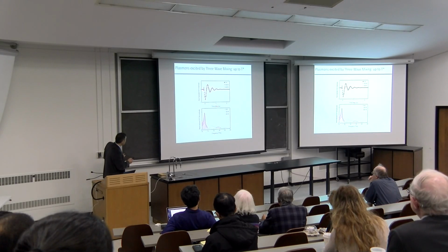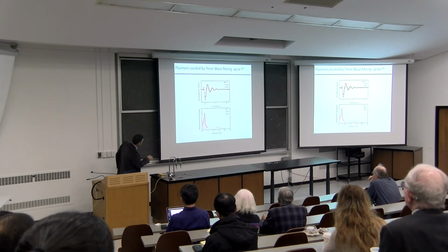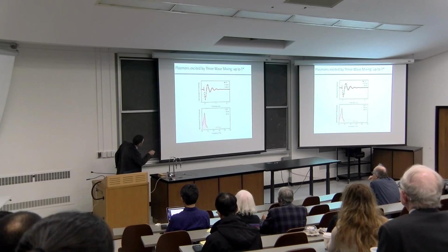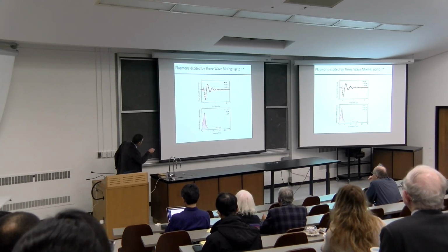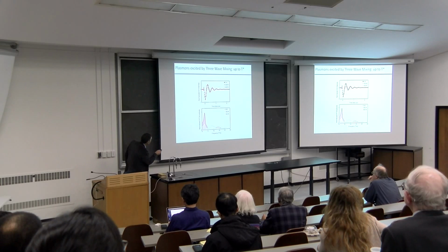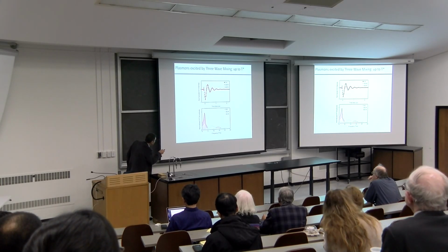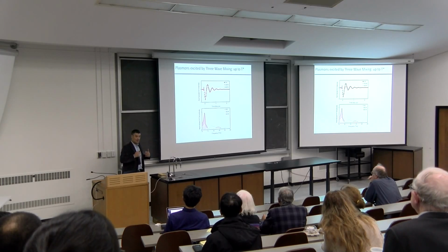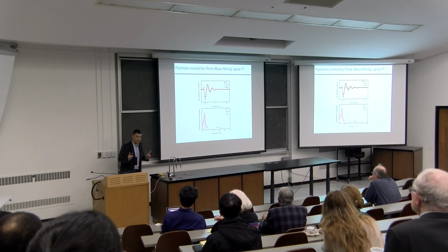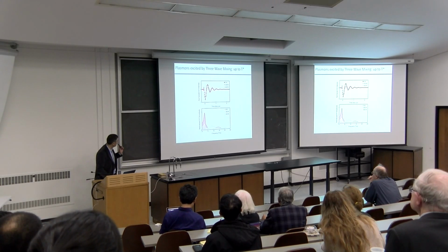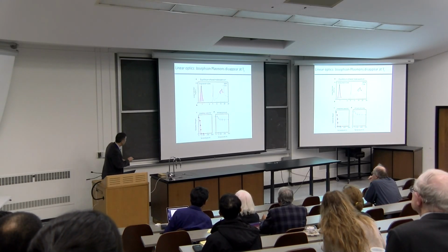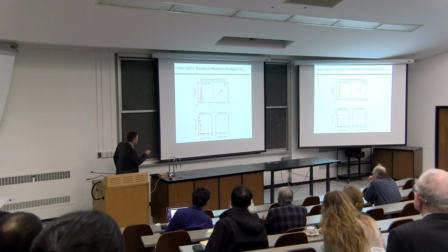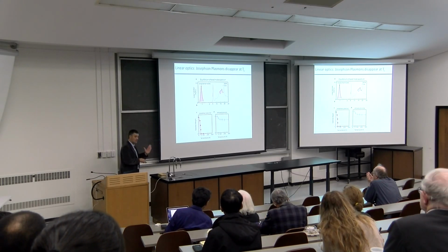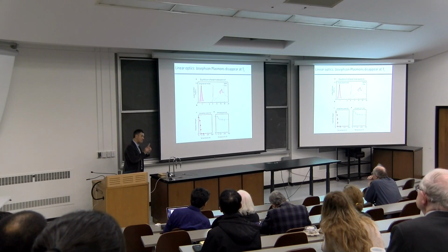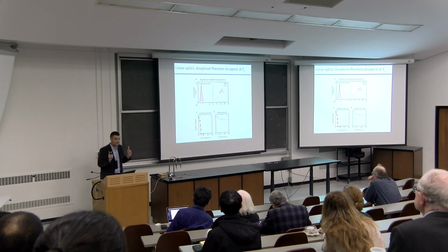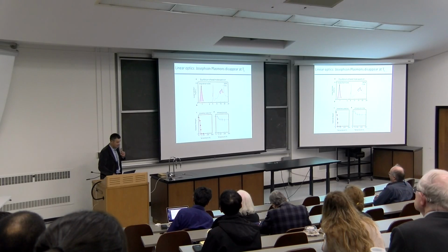Okay? So surprise, surprise, what happens is that by pumping these two phonons, this was the experiment I showed you before, it was at 5 Kelvin. When I go to 100, 200, and even at 300 Kelvin, I still see this Josephson plasma peak at finite momentum driven by my pump. Okay? So one important point that I don't think came across very clearly. This equilibrium peak is measured in equilibrium at k equals 0. My putative amplified fluctuations are measured at finite momentum. So these are two slightly different things.